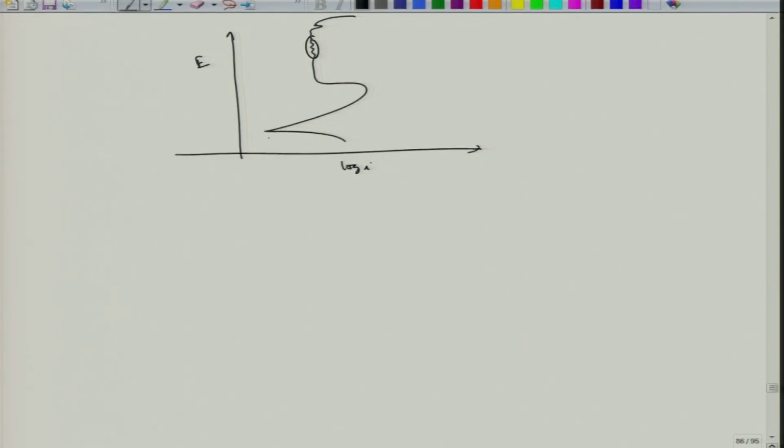So, those noises could be indicative of metastable pit formation. Now, one of those metastable pits can grow and form a stable pit, and then that stable pit keeps on increasing with the increasing potential.